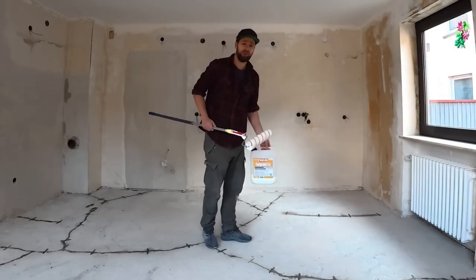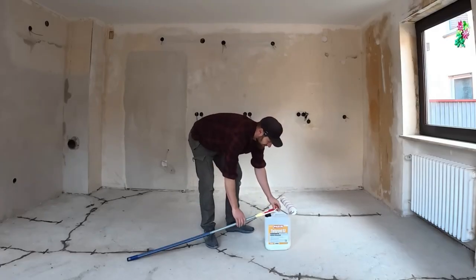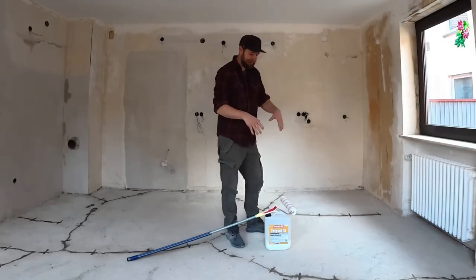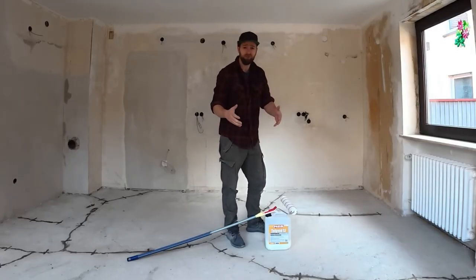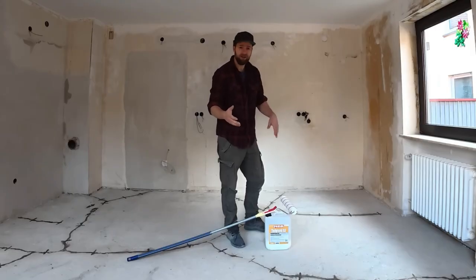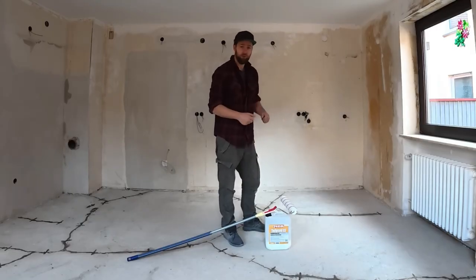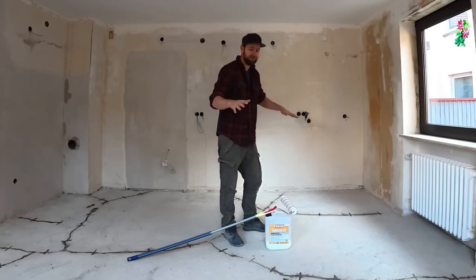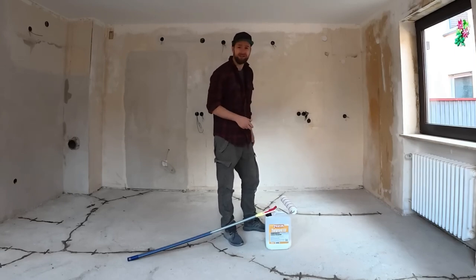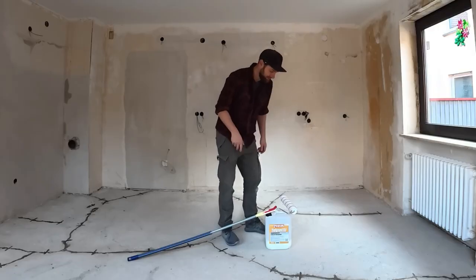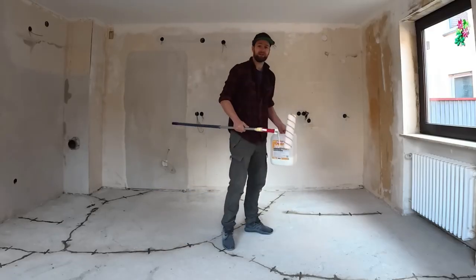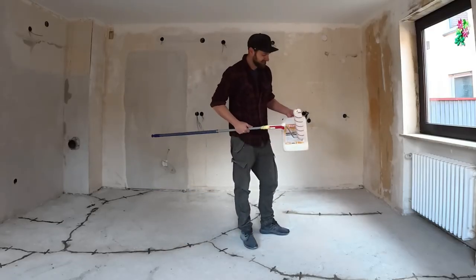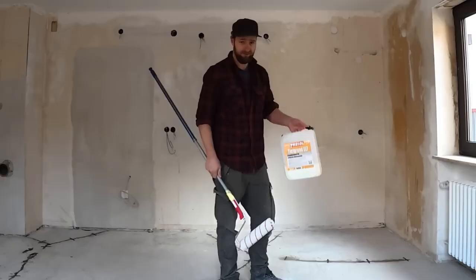This is an absolutely crucial step that often gets forgotten or skipped, but that can end badly, because right now the concrete floor is still porous and absorbs a lot of water. If we now apply our thin layer of filler, the floor will draw water out of the mortar, and then it can happen that the mortar literally burns on the surface. And then later you wonder why you have a dust desert instead of a proper floor. That's why you need to prime properly, because that drastically reduces the absorbency of the floor, and then you can work properly.